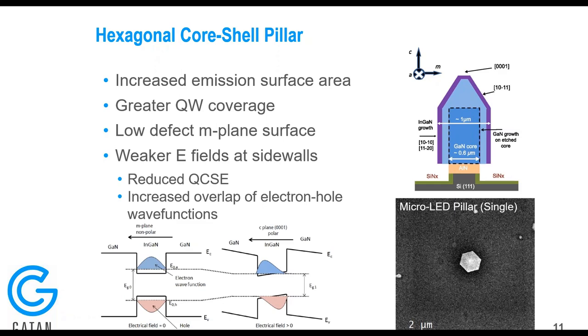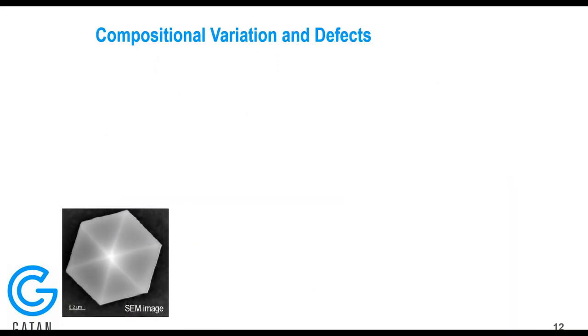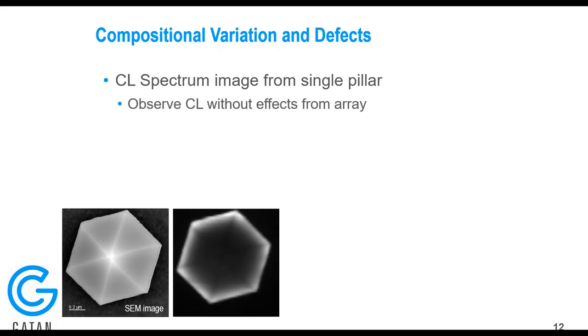So before we get into looking at the properties of a micro LED array, we should analyze a single pillar in order to determine what are the effects of the array and what are native to just the pillar. So first we can look through CL at compositional variation and defects in the sample. Here we have an SEM image from the top down of a hexagonal core shell pillar. We can take a spectrum image of that sample, and this is a spectrum image that's been stacked up so that it's relatively panchromatic. There's no selectivity of information on the light here. This is all of the light stacked up. And so we can see the relative intensity is such that, as we would kind of expect, most of the emission from that sample is coming from the outer walls of the pillar.